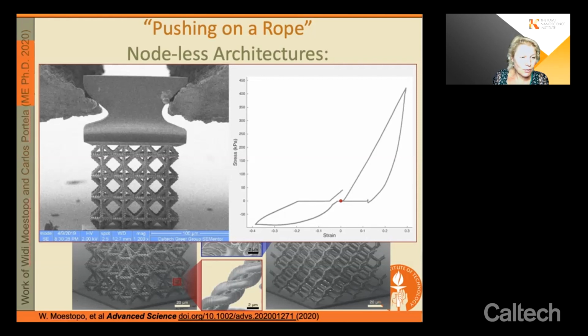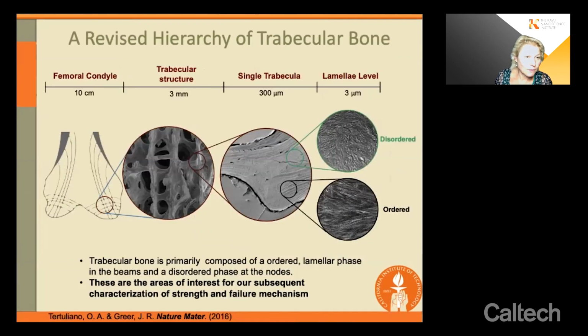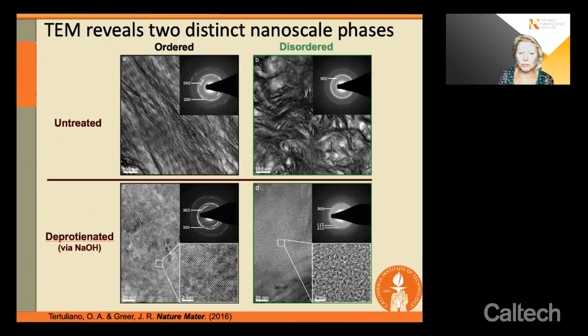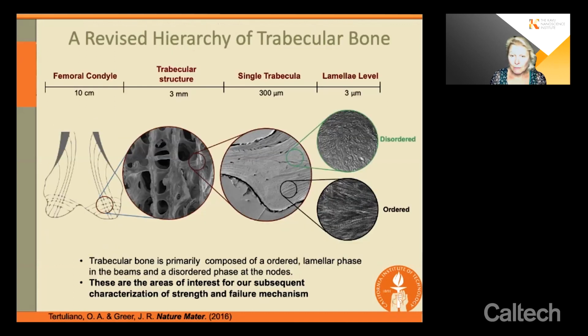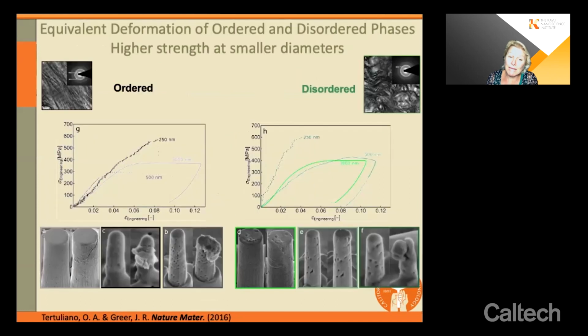So here's the work of my former student, Dr. Ottman Tertuliano, who worked directly with trabecular bone. What he was able to uncover is the very hierarchical length scales within a particular biomaterial. Here, of course, this is trabecular bone, where you can show that there are regions that are ordered, regions that are disordered, and then through separation of scales in different materials like extracellular matrix versus hydroxyapatite, it's possible to discern their mechanical properties from each individual phase.